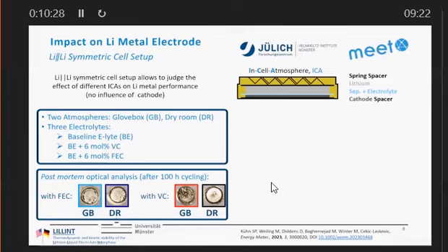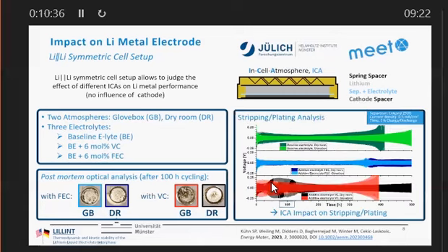And they are also different depending on whether we assemble the cell in the glove box, that means under argon, or in the dry room, that means under dry air. If we look at the cycling data for these lithium symmetric cells, for me, this is a cathode-free cell, we see that with FEC in the dry room, we get better cycle numbers, and with VC in the glove box, we get better cycle numbers. So depending on which additive we are using and which atmosphere we apply for cell assembly, we get very different cycle numbers.